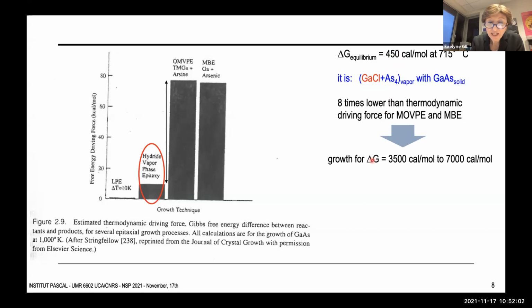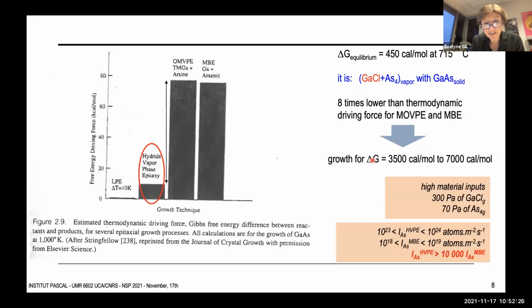Then free energy driving force ranging from 3,500 to some 7,000 calories per mole is sufficient to promote growth in the HVPE system. And this corresponds respectively to low supersaturation condition up to a medium supersaturation value. So I guess that if HVPE is often seen as a high supersaturation system, it is because one may confuse with high material inputs, high material flows that are at least, and that is true, 10,000 times higher than for MBE.